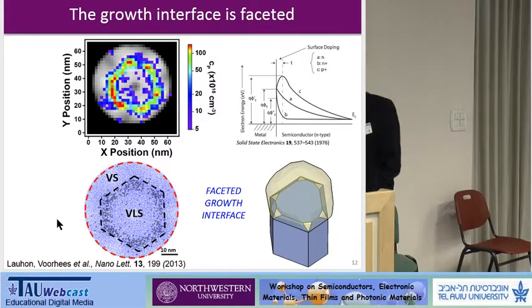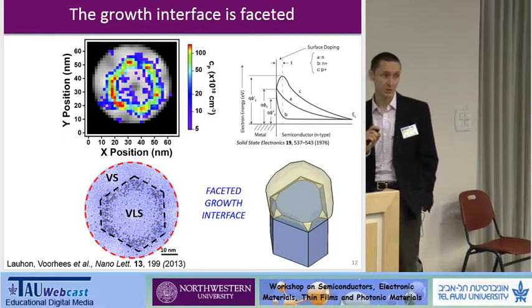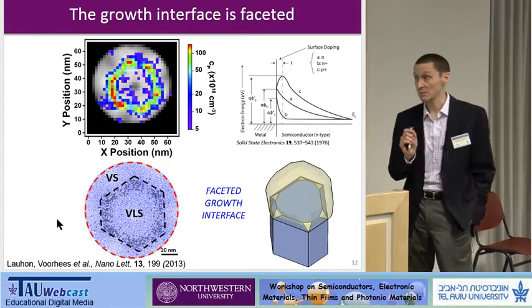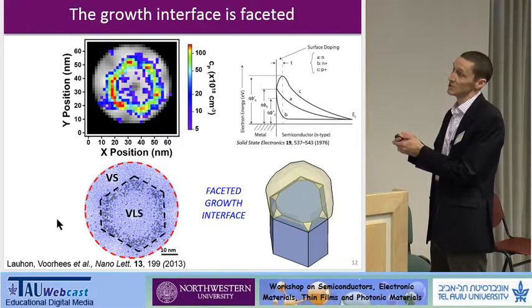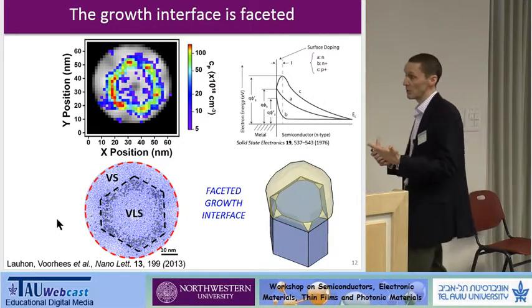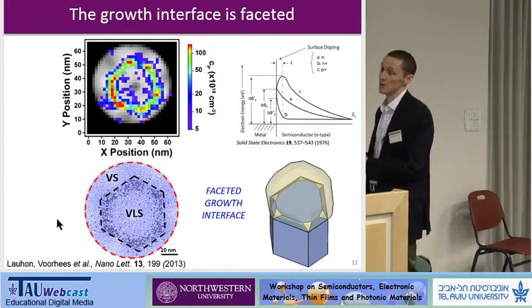And that's done intentionally in semiconductor devices to lower the Schottky barrier and thin the Schottky barrier to make good ohmic contacts, as illustrated here. So essentially going from A to B is what happens when you increase doping near the surface. You get a reduced barrier.